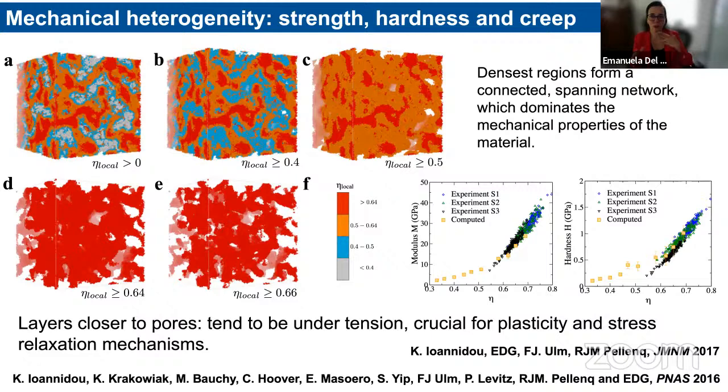And as we remove layer by layer, we end up with this very dense hard backbone, which is actually slightly under compression by the way we form it, and which corresponds to most of the strength that is measured through nanoindentation. And this type of analysis also tells us that, at least in this version of the cement cohesion that we have mimicked, you get this very hard backbone that is under compression, covered by a layer of material that is slightly softer and starts to be under tension as you approach the surface of the pores. So this gives a suggestion, and this is what we are working on at the moment, on where